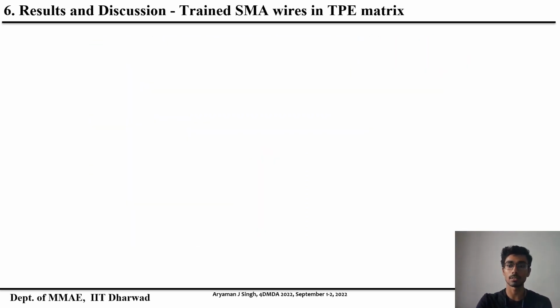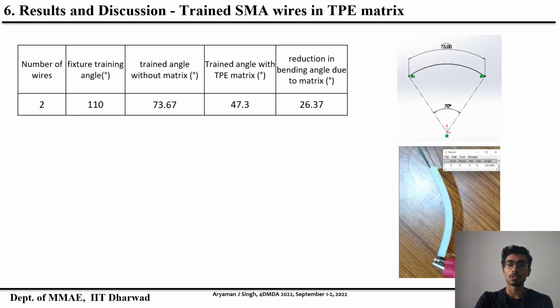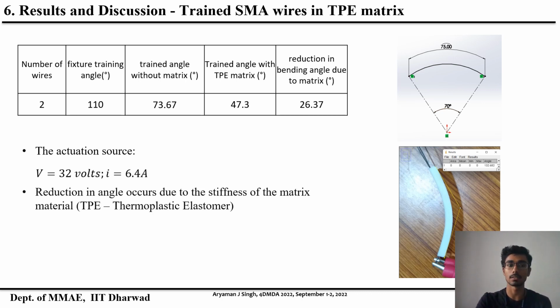Moving on to the results, it was observed for a similar actuator of different dimensions with 2 wires inserted into a TPE structure that the matrix reduced the bending angle of bare SMA wires by 26.37 degrees. Tabular data on this is shown.